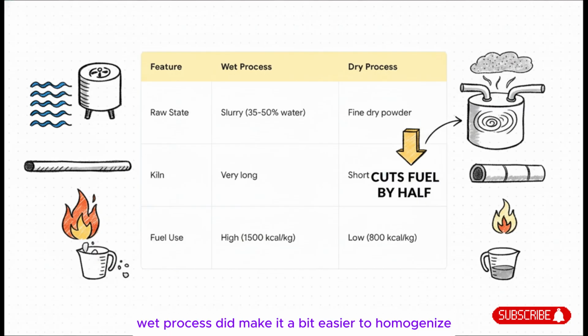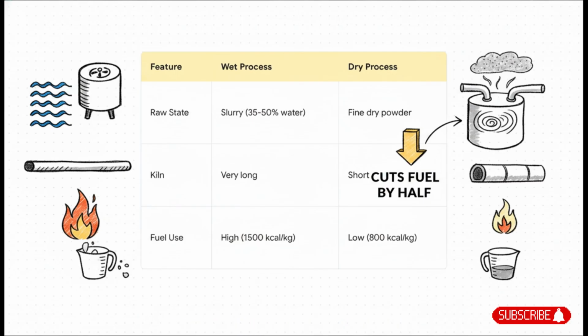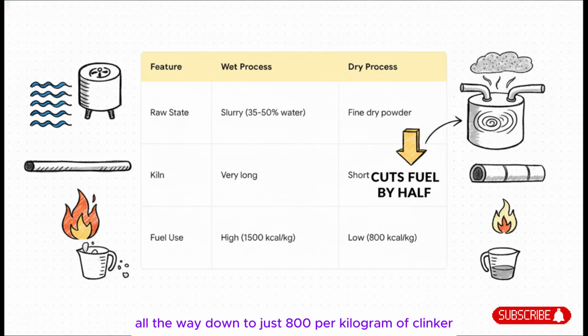Now, while the older wet process did make it a bit easier to homogenize the slurry, the modern dry process tackles that by utilizing that sophisticated air blending we talked about. And the massive payoff? Fuel efficiency. It literally cuts fuel consumption almost in half, dropping from 1,500 kilocalories all the way down to just 800 per kilogram of clinker.